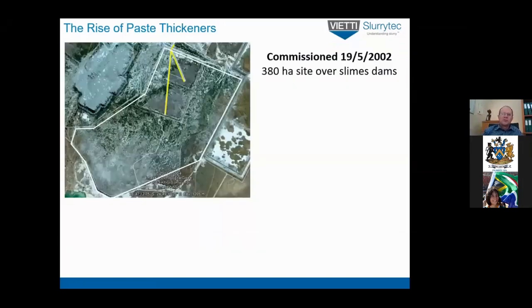This is the deposition site. So it was built on two old existing tailings dams. So this is the perimeter, but there's the old tailings dams, those squares there. The pipeline came from the plant there and then split into two branches, and they both ended there and there in case they needed to change the deposition point. So it was commissioned in about May 2002 over quite a big area. It's a 380 hectare site.